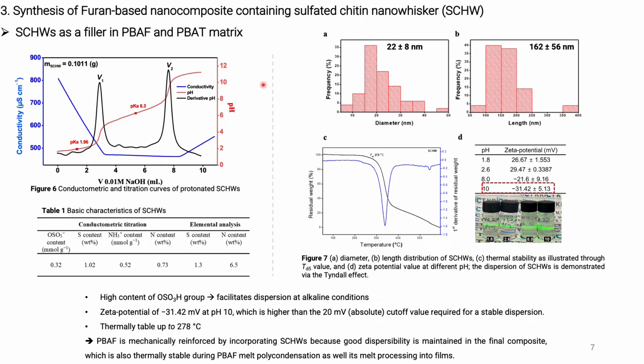And also, while conventional chitin nanomaterials produced by hydrochloric acid mediated hydrolysis are well known to disperse only in acidic media through protonation of their amino group, which electrostatically stabilizes the suspension, in contrast, the SCHW suspension with sulfate half-ester content of 0.32, like we can see here, is stable in an alkaline environment due to the deprotonation of the sulfate half-ester group. We can see the stable dispersion of SCHW in different alkaline conditions here.